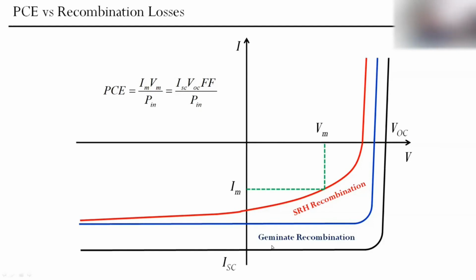However, if we add this geminate recombination, it means that we don't generate free charge carriers. And only the concentration of photo-generated free charge carriers defines how much quasi-Fermi levels, which describe their concentration, are split in the material of the active layer. That's why we lose VOC, because we have fewer free charge carriers, we have less splitting of quasi-Fermi levels, and we lose in short circuit current, because if we have fewer free charge carriers, there is less to be collected with electrodes and contribute to the short circuit current.